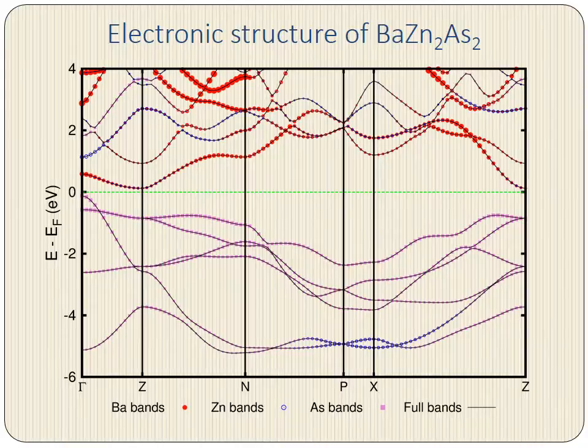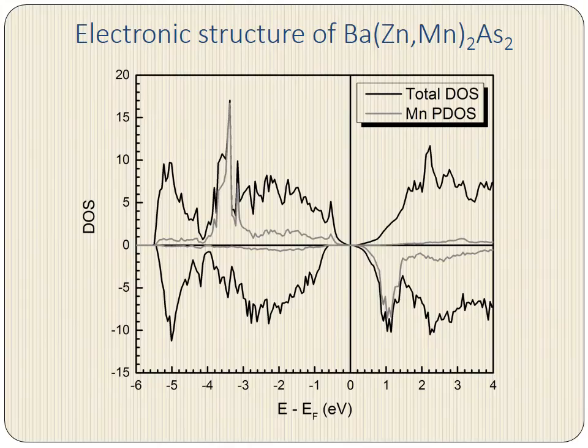Now, we want to see what happens when we add a manganese atom into this system, and in order to evaluate that, it's easier to look at the density of states. Here I plot the total spin-resolved density of states, as well as the manganese-resolved partial density of states. The sharp peaks that we see here and here are primarily of 3D electronic character, and we see that the majority states are fully occupied and the minority states are fully unoccupied.